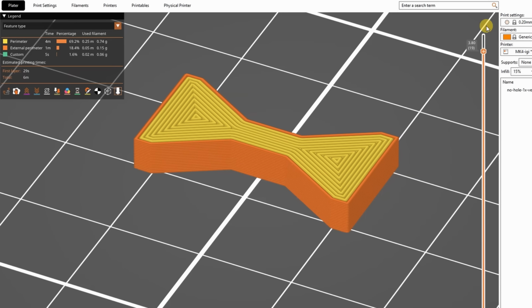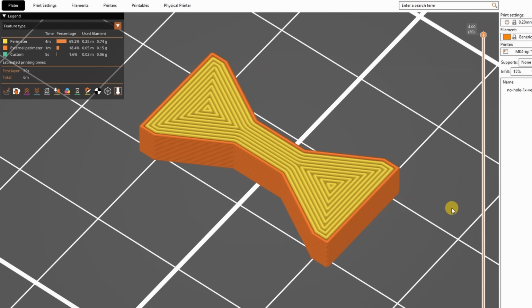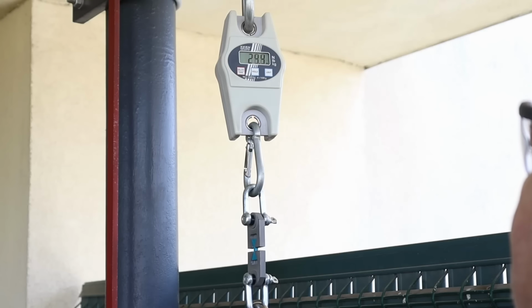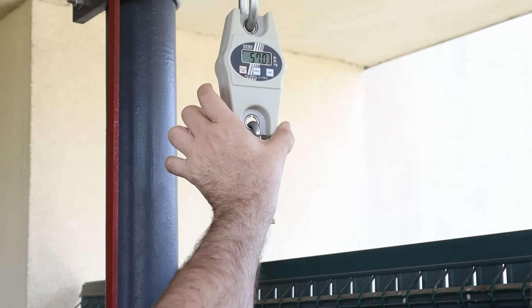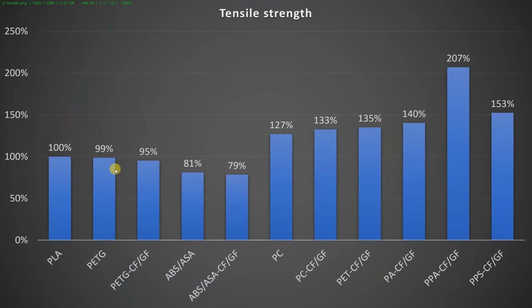Tensile strength. The object is printed in horizontal position with the smallest cross-section area of 4x4 mm, and I'm pulling it until the break. For basic materials, we can see that the PLA is the strongest and ABS ASA is the weakest, even if it is reinforced with the carbon or glass fibers. From engineering materials, more or less they are very similar, but a big jump we can see with the PPA-CF, which is almost too strong for my basic crane scale.